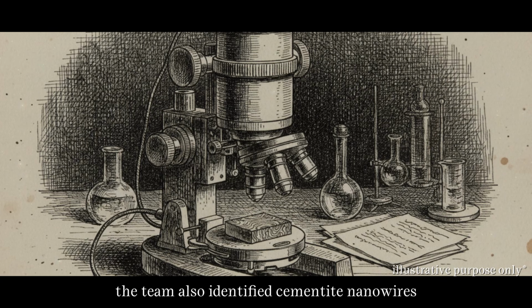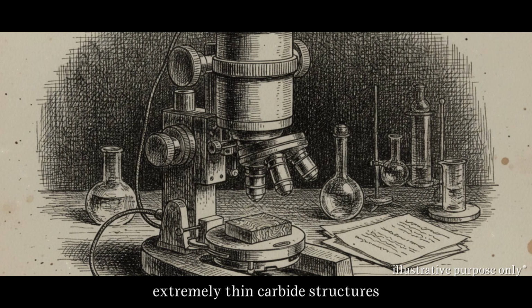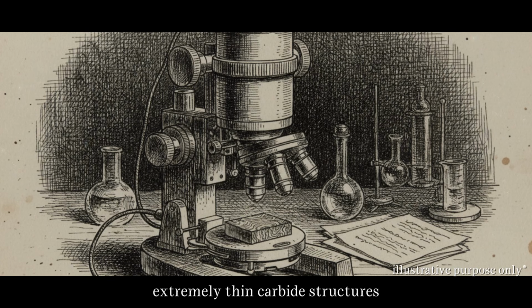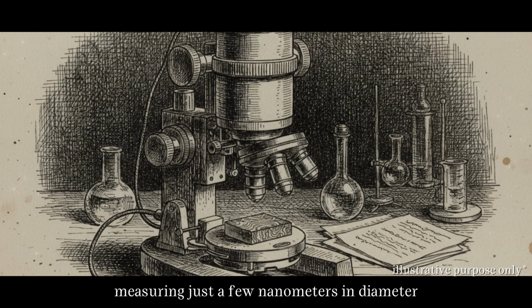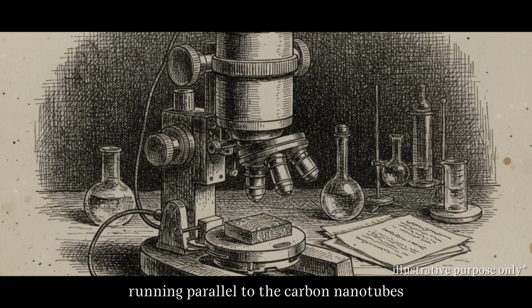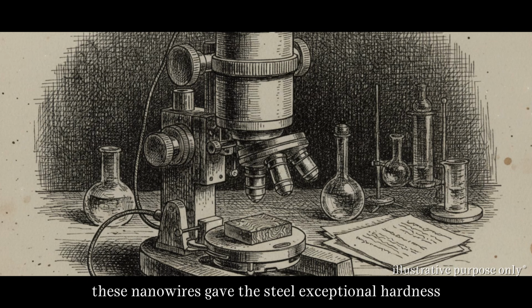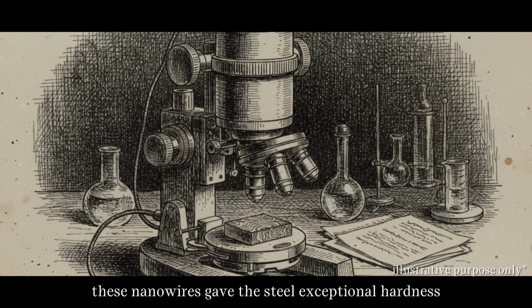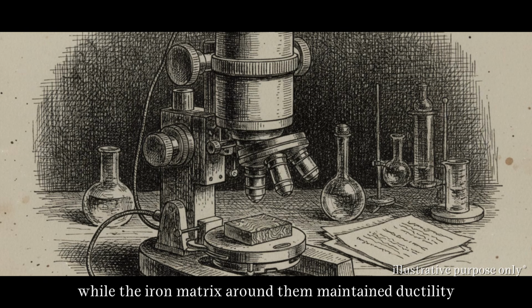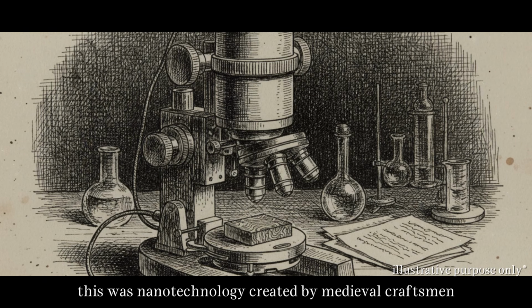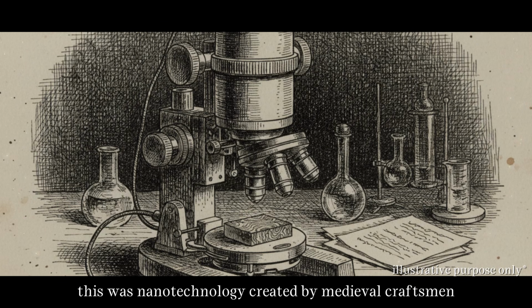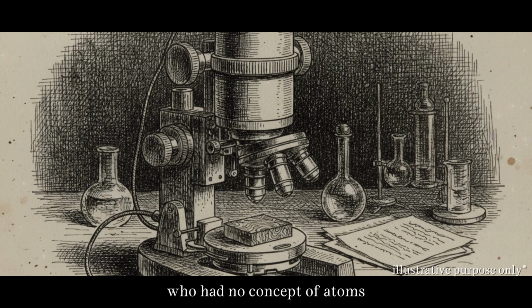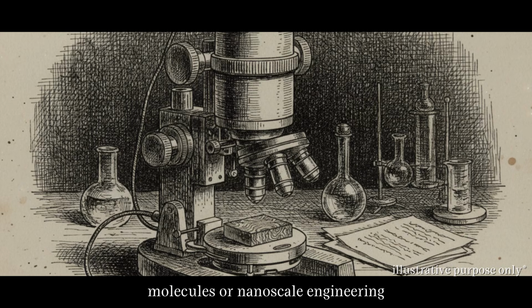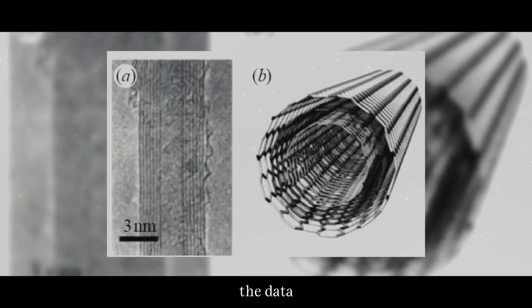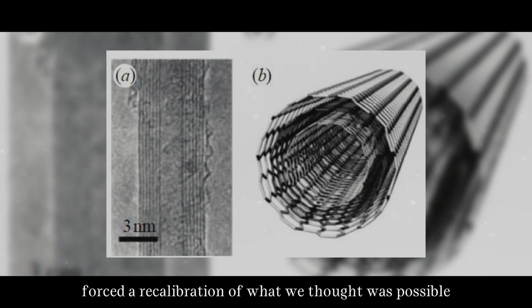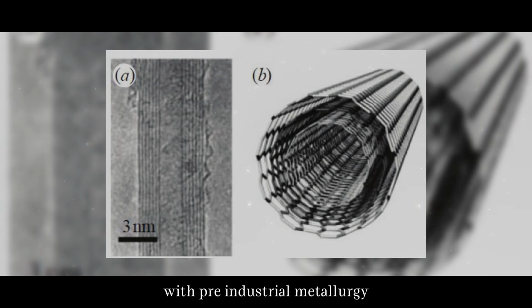The team also identified cementite nanowires, extremely thin carbide structures measuring just a few nanometers in diameter, running parallel to the carbon nanotubes. These nanowires gave the steel exceptional hardness, while the iron matrix around them maintained ductility. This was nanotechnology, created by medieval craftsmen who had no concept of atoms, molecules, or nanoscale engineering. The data forced a recalibration of what we thought was possible with pre-industrial metallurgy.